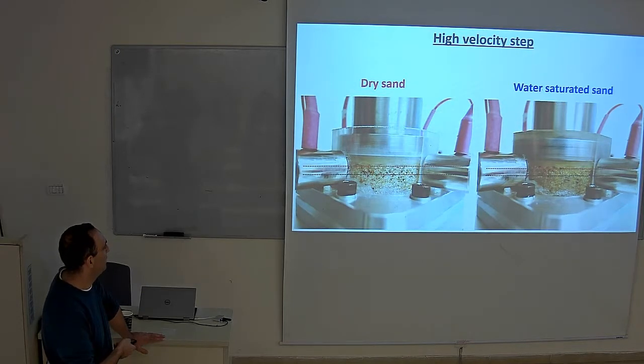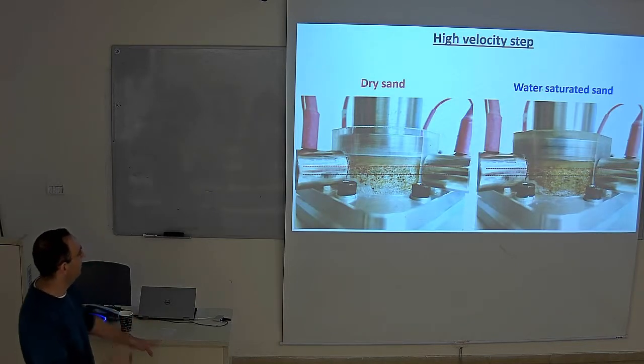The next is the high velocity step experiments. And again, there is a slight change. You will see that at the low velocity the particles are moving slower. They have a thicker band compared to the water saturated. However, it's not a big difference. So I'm not sure if that's the reason for the difference of the delta gap.